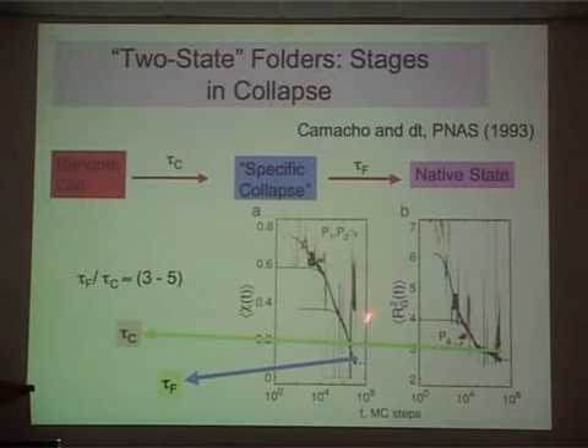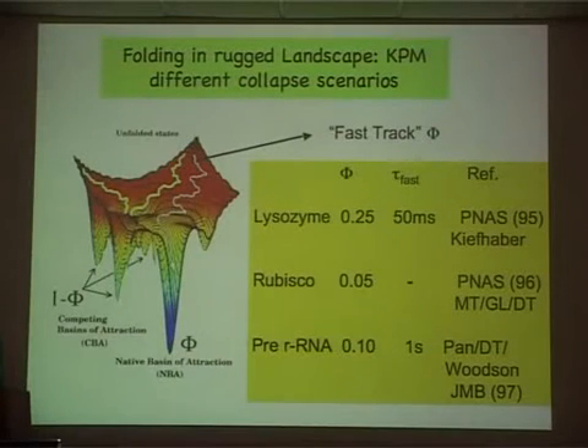So this is the radius of gyration squared as a function of time. This is a very old paper, and there are many newer papers. And you can see that this is a simple lattice model with just 25 or so residues as a function of time. And even here, the RG, in fact, does not decay exponentially, but there are stages in which it happens, and these multiple stages are the kinds of things that one needs to sort out experimentally, and this is a thing that I think Giant is quite interested in. So that's for a simple system.